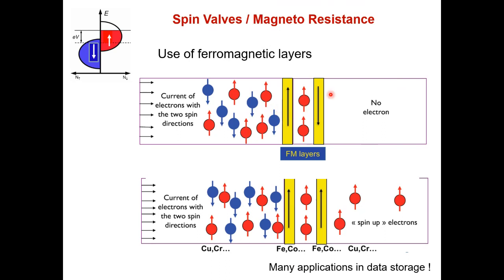but they are nowadays typically based on inorganic material. Now, of course, to get a good device, when you inject the spin up here, you want your spin up to go fast across the layer, but you don't want your spin to flip over during the path, during the travel, because otherwise you're losing your principle of selectivity. So you want the spin here to go fast and to keep the orientation of the spin. And here the current inorganic materials are very, very good to provide a very fast speed for the charges, but they are very bad in keeping the orientation of the spin.